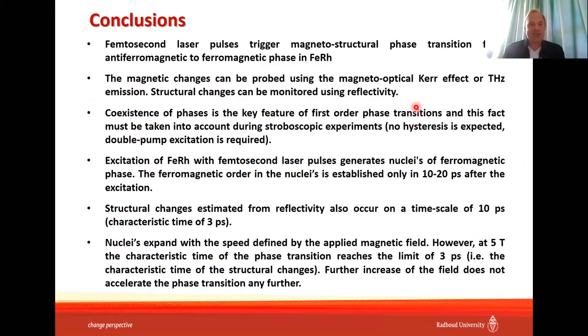So the conclusions. Femtosecond laser pulses trigger a magnetic structural phase transition from antiferromagnetic to ferromagnetic state. So it was known before, of course. It was a part that I put in the introduction. The magnetic changes can be probed using the magneto-optical Kerr effect or THz emission. Structural changes can be monitored using reflectivity. This is again a summary of what we knew before we started the measurements.